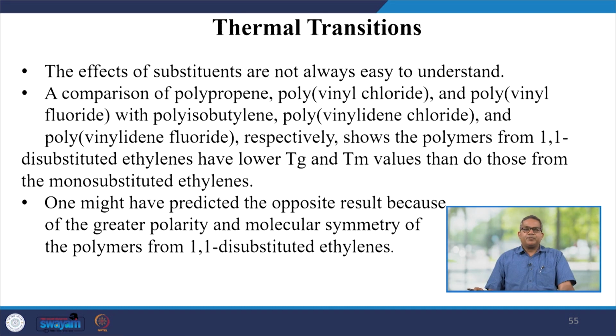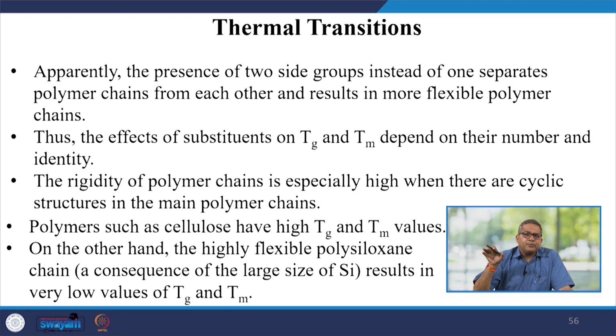The effect of substituents is not always easy to understand. Usually, consider the comparison of polypropylene, polyvinyl chloride, polyvinyl fluoride, polyisobutylene, polyvinylidene chloride and polyvinylidene fluoride. This shows the polymers from 1,1-disubstitution of ethylene. They have lower Tg and Tm values than do those from the monosubstituted ethylenes. Apparently, the presence of two side groups instead of one separates the polymer chains from each other and results in more flexible polymer chains. Therefore, the effect of substituents on the glass transition temperature and Tm depends on the number and identity. The rigidity of the polymer chain is especially high when there are cyclic structures in the main polymer chains.